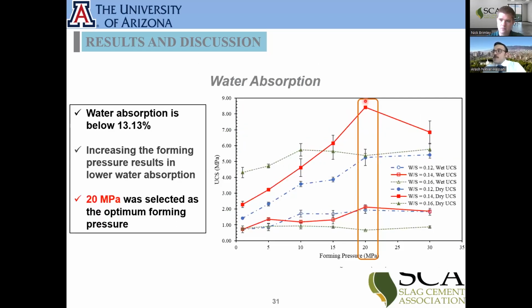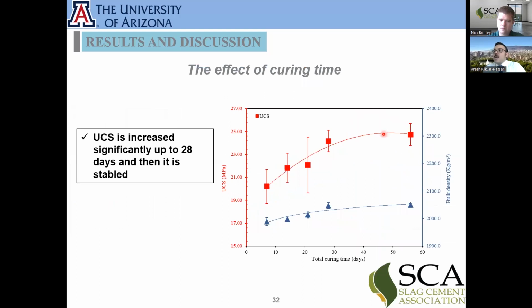With this maximum sample we have, we tested the samples for different curing times. But we didn't put the samples in the oven anymore. So all the results after 7 days are for samples that stayed in the laboratory environment at room temperature. And you see, even at room temperature, we have some growth in the sample strength over time, and we tested the samples up to 56 days, and we have the result.